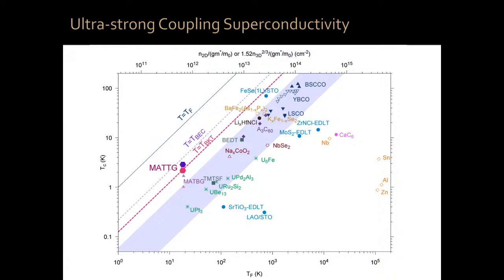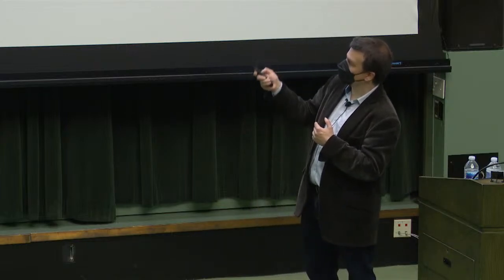With these Moire systems, okay, we don't know yet how to do that. They're very diluted, okay? These Moire wavelengths are very large, of the order of 10 nanometers. That's why you get a super small Fermi temperature, okay? An idea that some people told me is, oh, maybe if we can modify the magic angle condition, for example, with pressure, such that you can do this at larger angles. Larger angles means smaller Moire wavelength, so you're riding up in density.